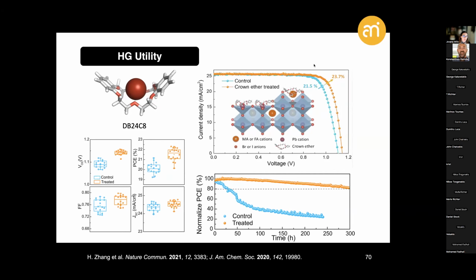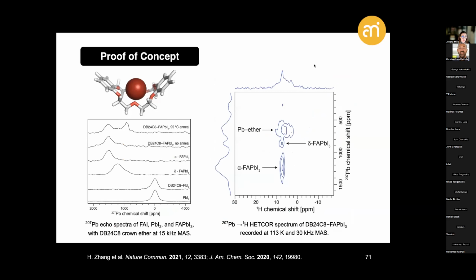which were assessed by using, once more, solid state NMR spectroscopy, where the binding, for example, of the lead cations was assessed by both lead NMR experiments using a combination of different precursors and the resulting modulated perovskite, as well as their heteronuclear correlations, in this case correlating the chemical environments of the lead with those of the protons, especially of those of the crown ether, whose presence suggests their existence in the close nanoscale proximity that is relevant to demonstrate their